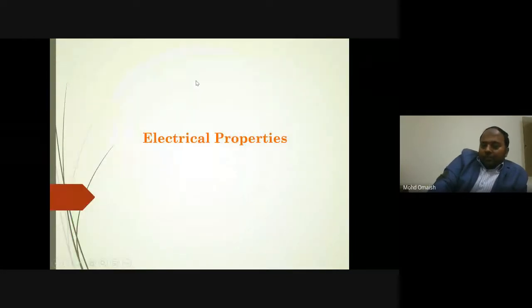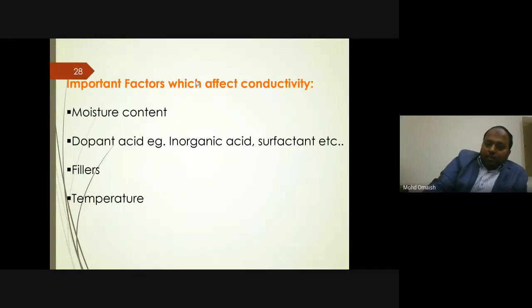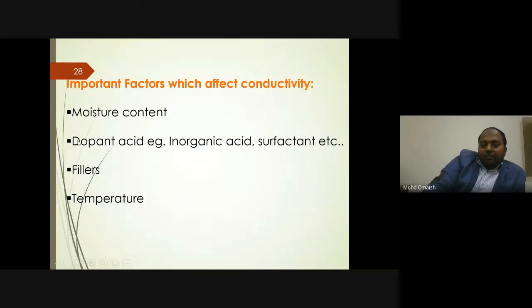So coming on to the electrical properties, the electrical property of a conducting polymer depends on the moisture content, the dopant acid, that is inorganic acid, surfactant or mineral acids, fillers, and temperature. As per my experience, for highly conductive polyaniline, the dopant acid is more important than the filler. The filler can impart a little bit of conductivity and stability, but if you want very high conductivity, you can use a good dopant like paratoluene sulfonic acid or camphor sulfonic acid.